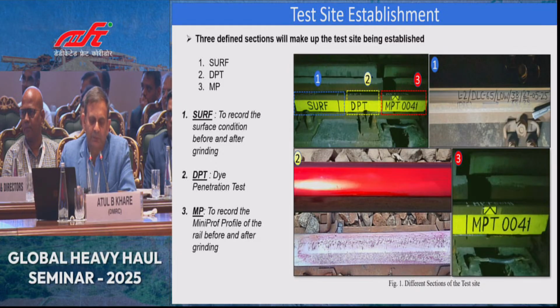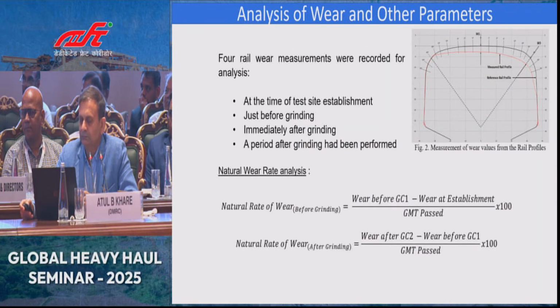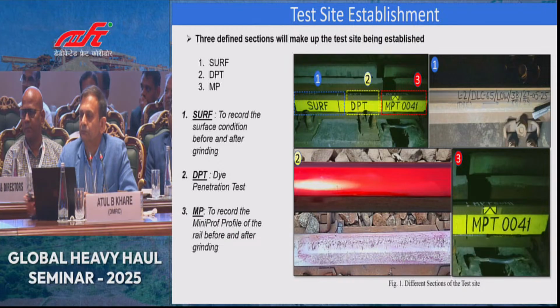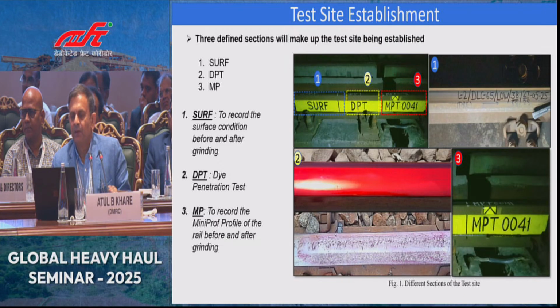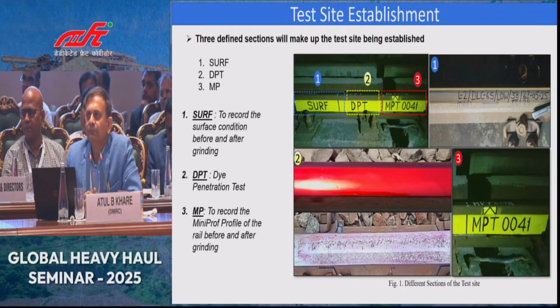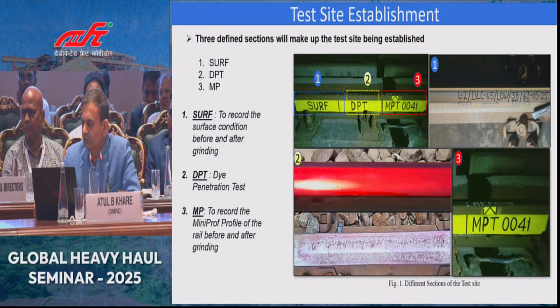For this purpose, we have established test sites at different locations, and these test sites are basically to monitor the surface condition, and we are carrying out dye penetration tests, and we are also measuring the profile with Miniprof.